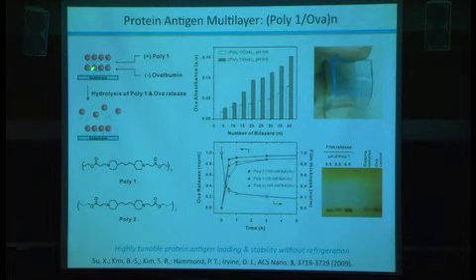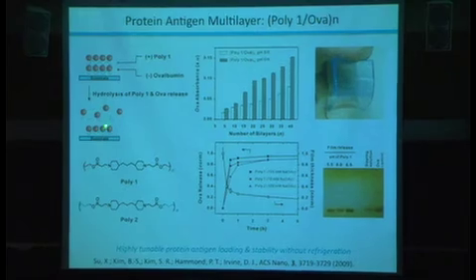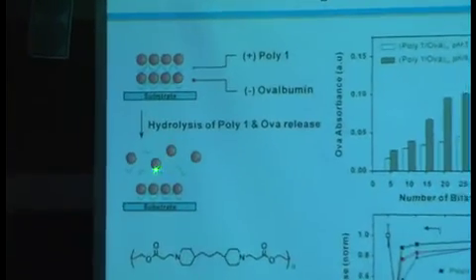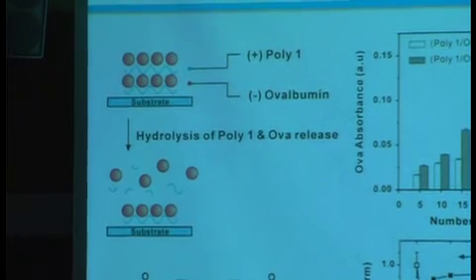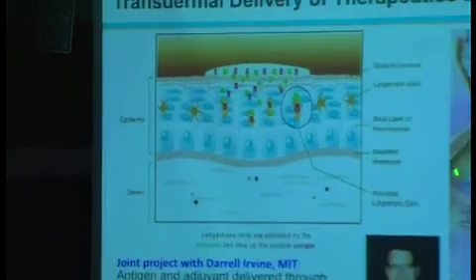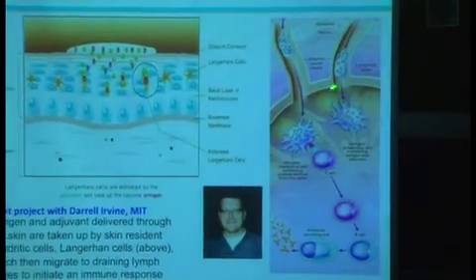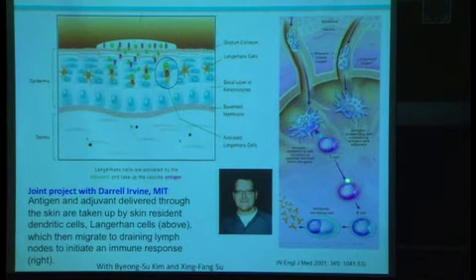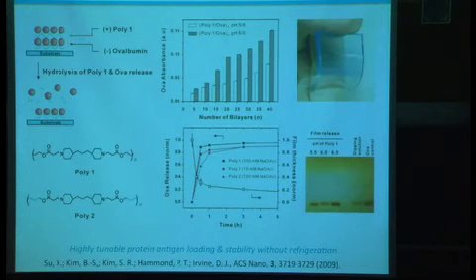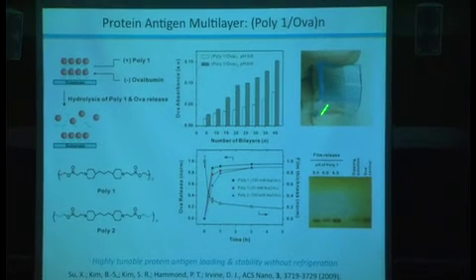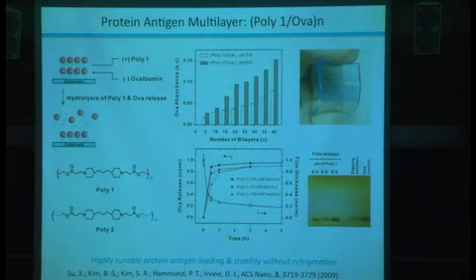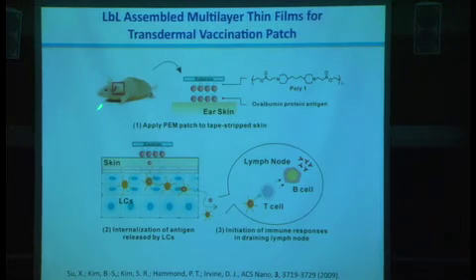We actually were interested in layering films onto a flexible substrate that contained an antigen of some kind, and then applying it so that we could actually use it as a vaccine. And if I go back one, the idea is that then we would have the dendritic cells in the skin, the Langerhans cells, take up the protein and begin signaling T cells and B cells, the other immunological cells in the lymph node, to build an immune response. So in our early work, we coated a polydimethylsiloxane sheet with these layer-by-layer films. We would tape strip a mouse's ear so that we remove the stratum corneum, which is the most difficult layer to penetrate. And we place our layer-by-layer film on top of the mouse and then observe what happened.